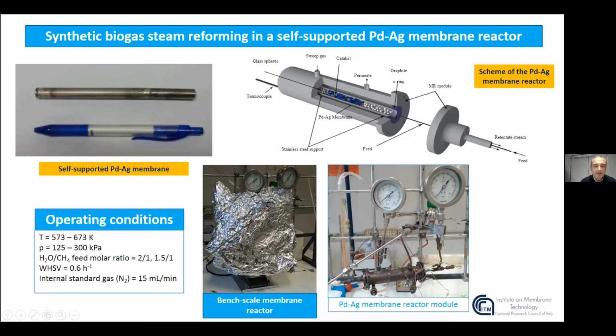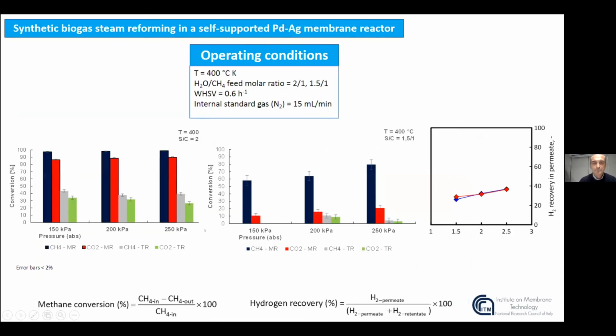And here under operation, we use a temperature range of 300 to 400 Celsius degrees and a reaction pressure up to 3 bar, analyzing the steam to methane feed molar ratio equal to stoichiometric values and under defect of steam at a constant space velocity, and using an internal standard gas procedure in order to validate the experimental results.